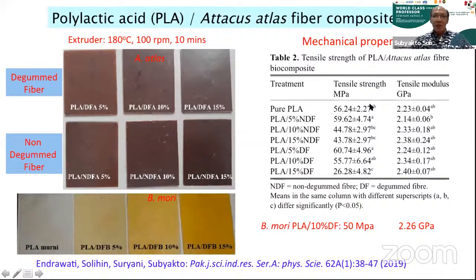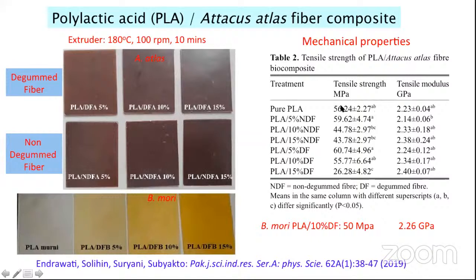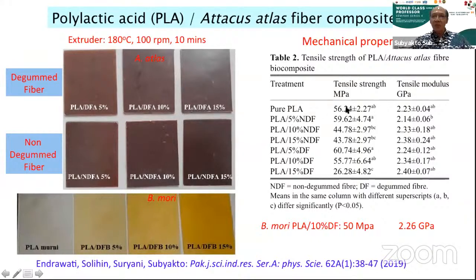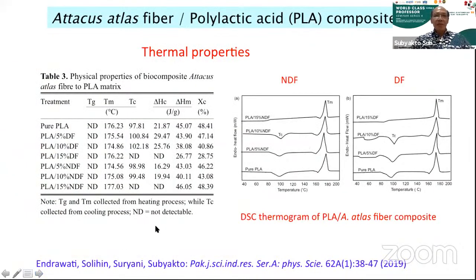And if we compare the strength, tensile strength and tensile modulus, pure PLA compared to this, where we added the fiber, there's a slight increase, especially at 5%. And we compare with Bombyx mori, almost similar mechanical strength. And also we check the thermal properties, and actually the melting temperature is quite similar to pure PLA.